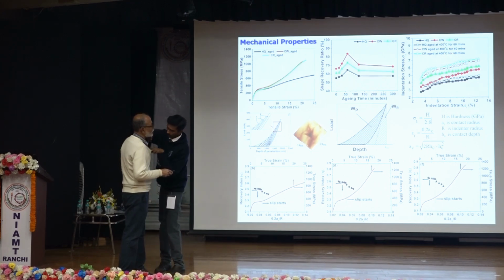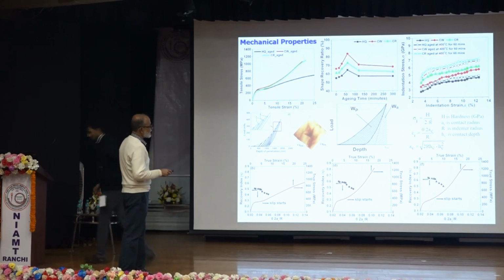There are two indenters, Berkovich and spherical indenter. We have adopted the spherical indenter as recommended for determining stress strain curve. So AC is the contact radius, R is the radius of the indenter, and H is the contact depth. So you can measure H and R physically, and you can determine AC. So that's how we have created the plot.